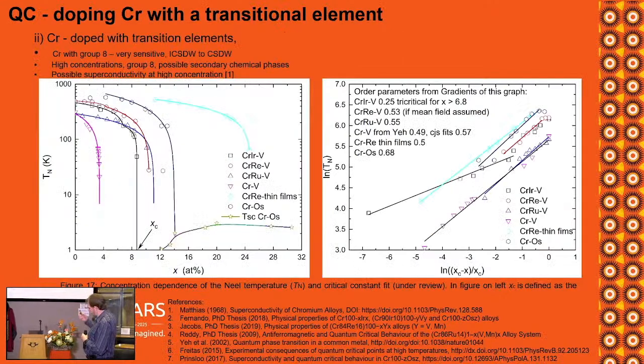Now, I've shown you about non-transition elements, but we also did transition elements, the same as those first phase diagrams. We actually studied concentrations far beyond 5. The trick, though, in the group 8s, is iridium, ruthenium, those, when you add too much, the crystal structure starts to change. So then with your magnetism, you're not sure, is it because of the BCC lattice, this body-centered cubic crystal structure, or because you're now studying a different crystallographic phase as another binary in your system? Another way we get around this is we start adding vanadium. Vanadium has 1 electron less than chrome. It makes the control a little bit easier.